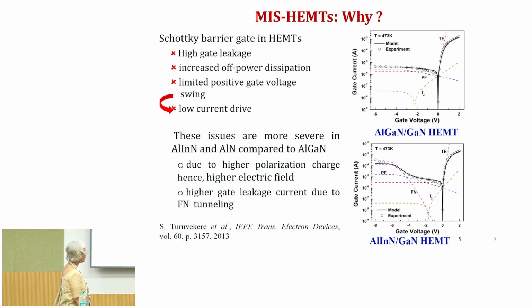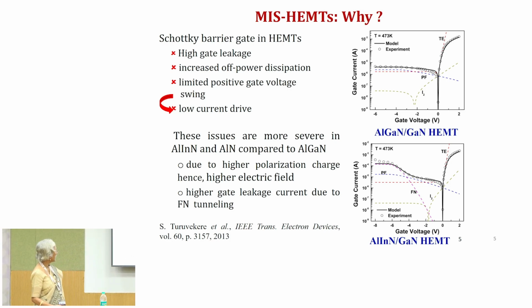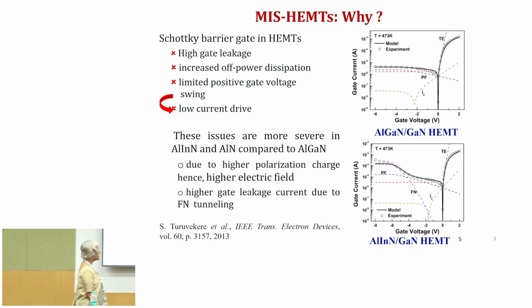Not only that, if you look carefully, you will find that in the case of the aluminum gallium nitride HEMT, the leakage current is dominated by the Poole-Frenkel mechanism. PF stands for Poole-Frenkel. Whereas, in the aluminum indium nitride gallium nitride HEMT, beyond a certain gate voltage, it is also dominated by Fowler-Nordheim tunneling. So, all these leakage current components add up, and therefore, we have a very high leakage current in the case of aluminum indium nitride. So, as I said, we have higher polarization charge and therefore higher electric field, which is good in a sense, but which is bad because the leakage current is also going to be much higher due to this high electric field.